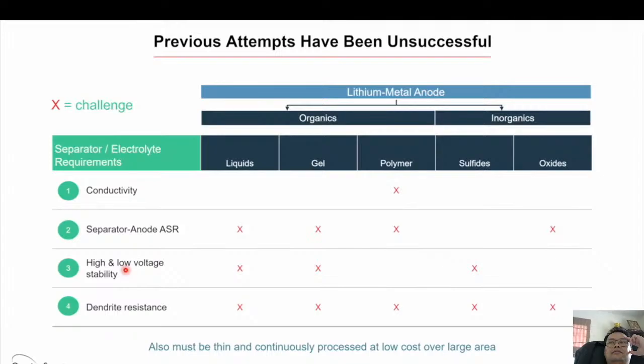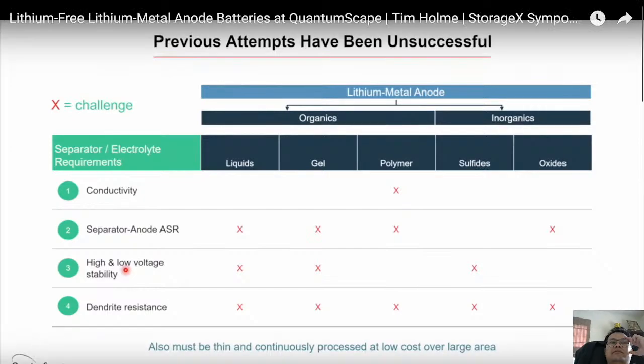So the 80 orders of magnitude of lithium activity, it's like saying you have metallic lithium on the anode side and 10 to the minus 80 lithium activity on the cathode side would be 1 atom of lithium per atom in the universe. It's just a huge range of lithium activity. So for a material to be stable across that full range is extremely challenging.